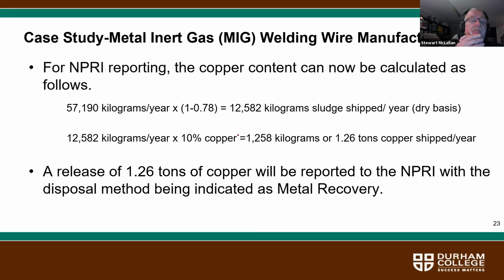All right. For NPRI reporting, the copper content can now be calculated as follows, because we know that we have 57,190 kilograms generated per year. We multiply that by 1 minus 0.78 because the sludge contains 78% moisture. There is only actually 22% dry sludge present. So your 57,190 kilograms per year becomes 12,582 kilograms of dry sludge shipped per year on a dry basis, right? 12,582 kilograms per year multiplied by 10% copper equals 1,258 kilograms, or 1.26 tons, of copper shipped per year.